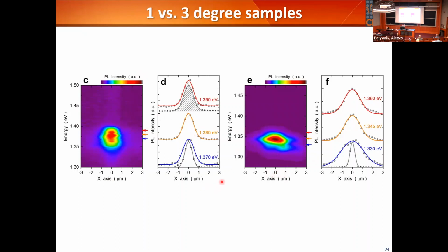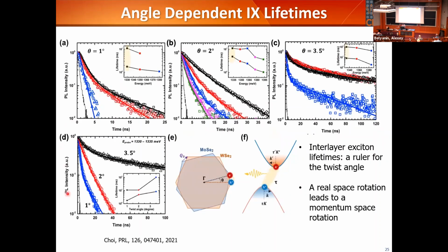With very low excitation density, the excitons are moving in the 3 degree sample, because the Moiré supercell is smaller, so they now can hop around. Another reason is that they live longer. I only want you to see the bottom plot. So these are samples at 1 degree, 2 degree, 3 degree, 3.5 degree.